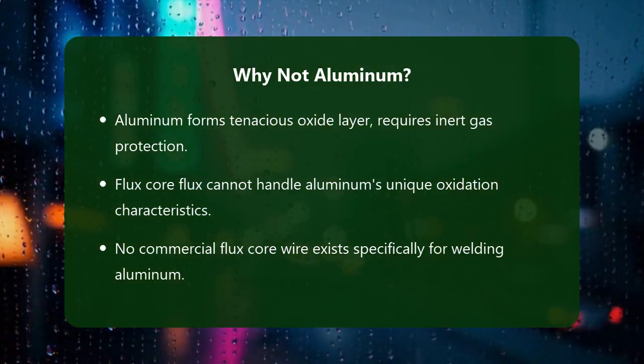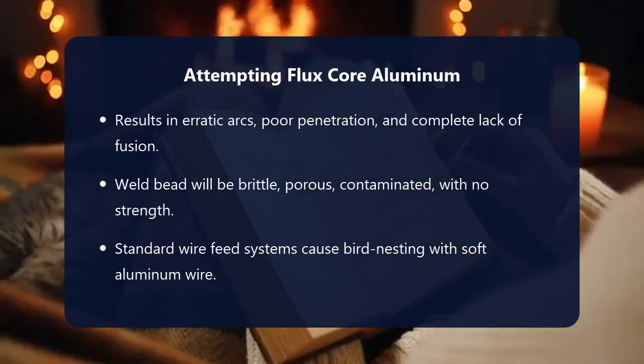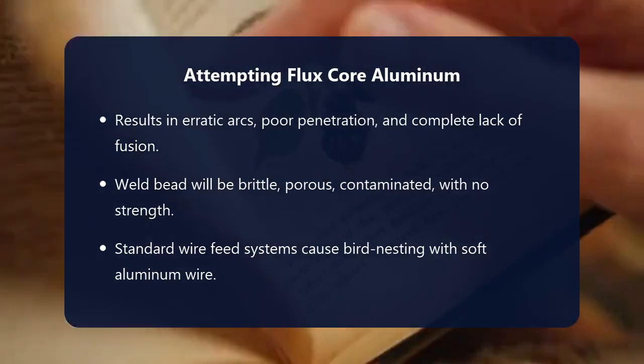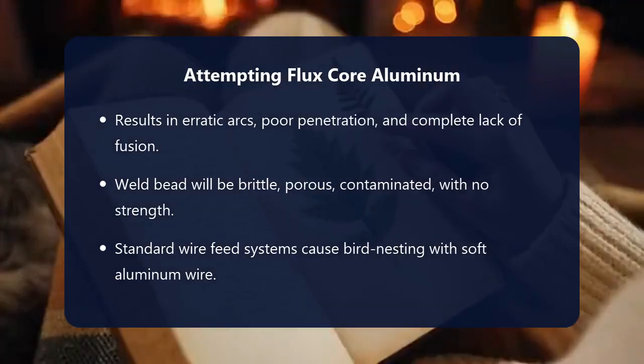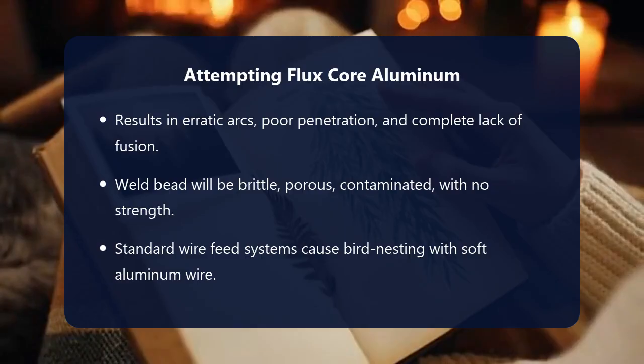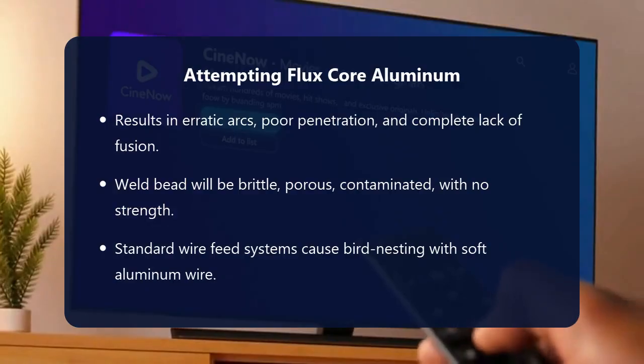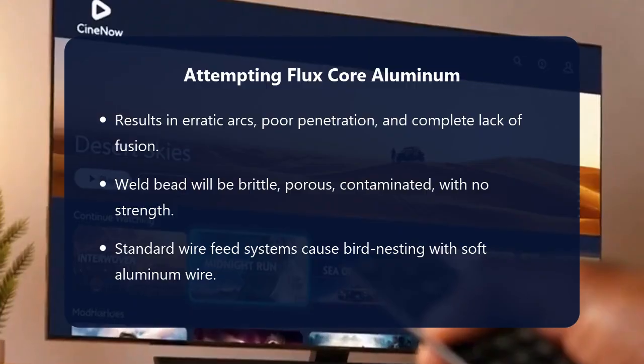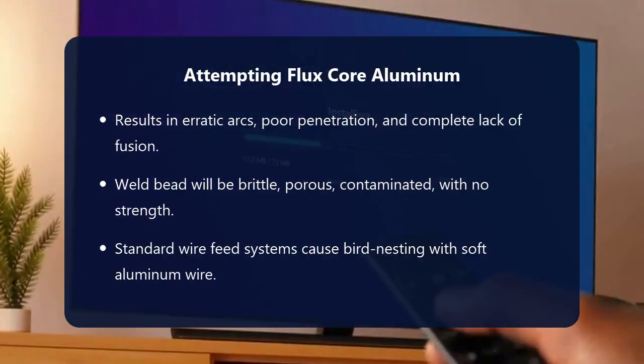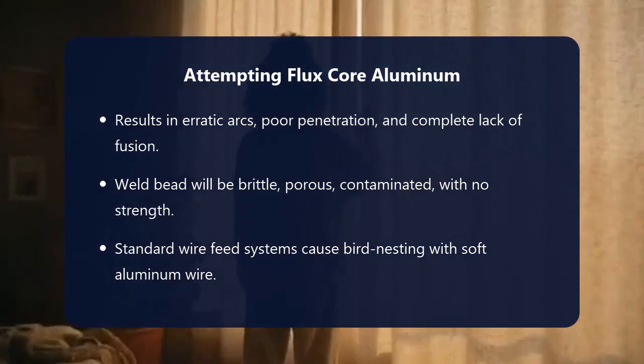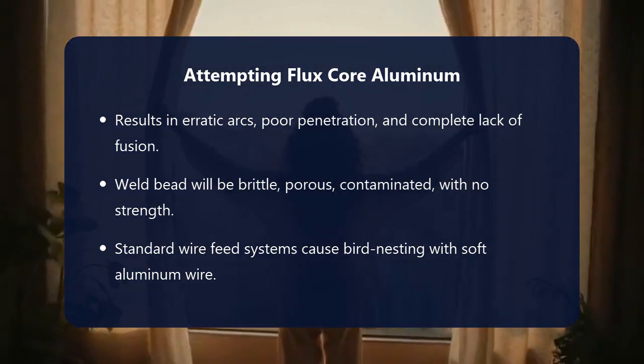You would likely experience incredibly erratic arcs, poor penetration, and a complete lack of fusion between the aluminum pieces. The weld bead, if you could even call it that, would be extremely brittle, porous, and heavily contaminated, possessing virtually no structural integrity. The slag produced by the flux core would also be an unwanted contaminant on an aluminum surface. Furthermore, the wire feed system and gun liner in most flux core welders are designed for steel wire, which is harder and has different feeding characteristics than soft aluminum wire. Trying to push soft aluminum wire through a standard steel liner would lead to constant bird nesting and feeding issues.